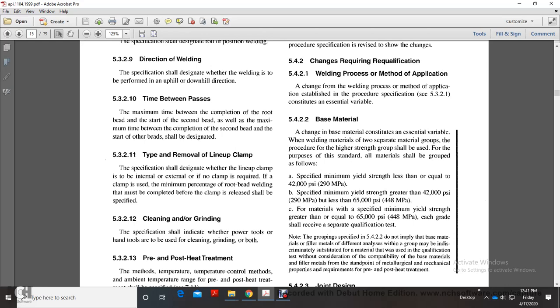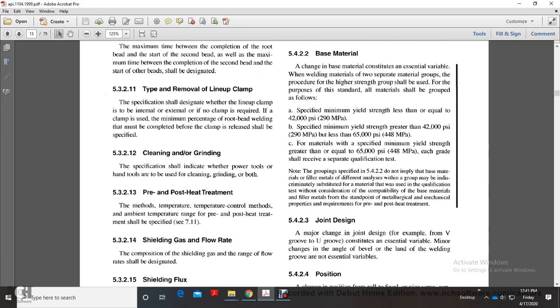All materials shall be grouped as follows: specified minimum yield strength less than or equal to 42,000 psi; specified minimum yield strength greater than 42,000 psi but less than 65,000 psi; and for materials with specified minimum yield strength greater than or equal to 65,000 psi, each grade shall receive a separate qualification test.